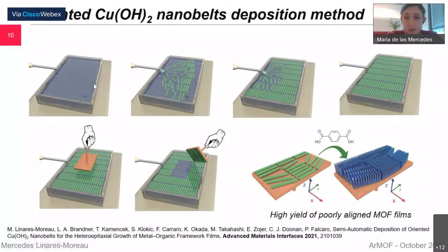This basin is filled with water, and we use a syringe pump to inject a dispersion of the nanobelts on the water surface. So by controlling the injected volume and the time, we can stack these nanobelts to form a full film on the water surface. And then with a substrate, we collect this film and create the oriented copper hydroxide substrate, which can then be converted to an oriented MOF film. Typically this step was performed manually, but we found that when you want to make a large number of samples, this has some problems because the reproducibility is low.